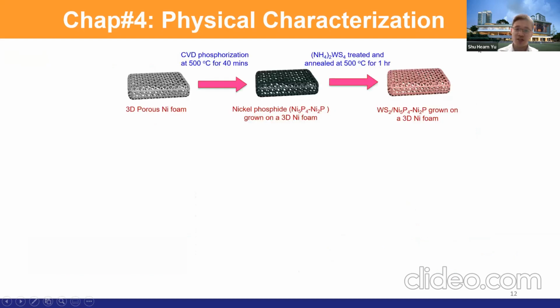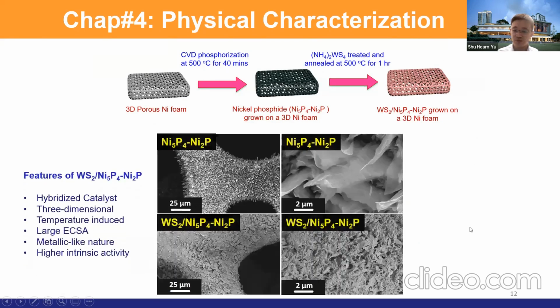So basically, this is the step by which I perform the experiment. This is a 3D nickel foam, pristine 3D nickel foam. And then I phosphorize it at 500 degrees C, and then I treat it with the WS2 precursor. I soak the template into the solution, and then I anneal it at 500 degrees C for 1 hour. So this is the catalyst I got.